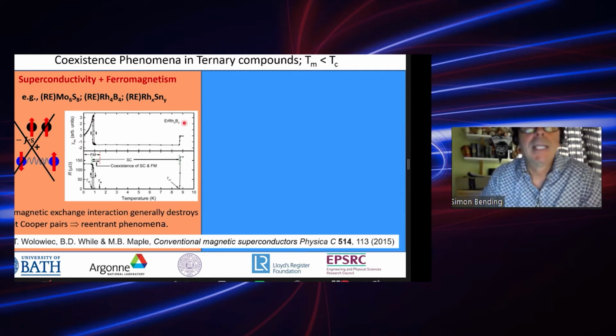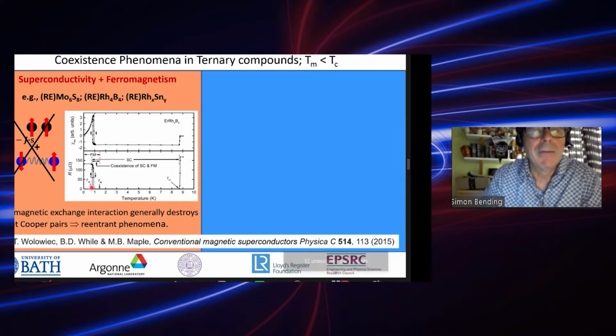Here I show an example taken from the system erbium rhodium boride. This exhibits a superconducting transition. If we look at the resistance versus temperature plot here, it shows a superconducting transition just below 9 Kelvin. And then there is an onset of a ferromagnetic state at about 1.4 Kelvin, as indicated by this arrow here. And we have a very narrow coexistence region where the sample remains superconducting. And then at about 0.9 Kelvin or so, we have a reentrance to a normal state where the superconductivity is destroyed by the exchange interaction due to this ordered ferromagnetic state which is coexisting with it.